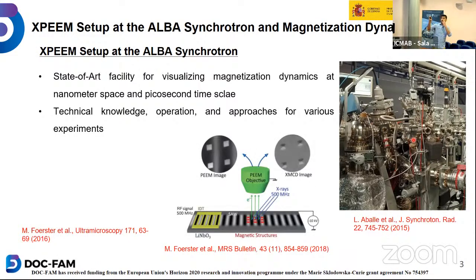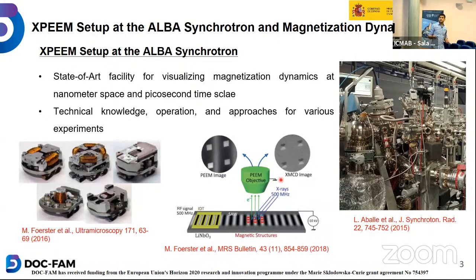This is how we see the magnetization dynamics, or magnetic behavior, in the films or in the material. For example, consider that we have a film, and X-rays coming in are incident on the sample. Then we have an objective lens, at high voltage, and the electrons leave the sample and go to the lens, and from there we can see, as you can see here, the PEEM image, and after analysis we get this XMCD image. In this way we get the XMCD image, which tells us about the magnetization states or magnetization behavior of the sample. In this, we use different kinds of sample holders.